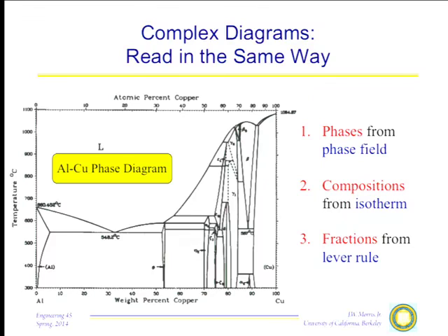It turns out to be actually very relevant to certain reactions that happen in solders, because aluminum can be a useful solute to add to tin copper solders, which are of interest as lead-free solders. And so what's happening up here, the copper-rich side of this aluminum copper diagram, turns out to be of significant interest in what the aluminum will do when you put it into a tin copper solder. So all these little regions up here, which are very hard to get hold of, are a matter of some dispute at the moment. But think something like this.